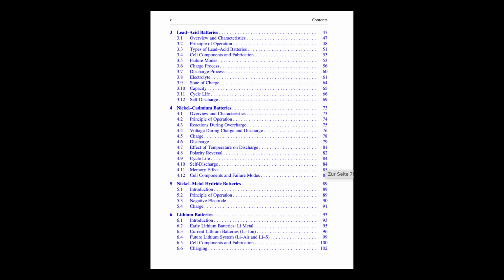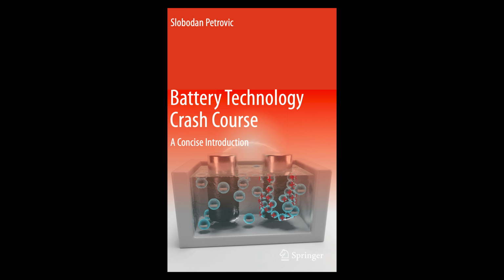Okay, one last time on the memory effect, with figures 4.14 and 4.15. Right. These figures reinforce the idea. It's caused by cadmium crystal growth. Figure 4.15 shows that, often triggered by shallow repetitive cycling or long inactivity. Figure 4.14 conditions. But again, Petrovic emphasizes it's usually reversible with full discharge cycles. Not a permanent failure mode in most cases, and modern designs mitigate it somewhat.